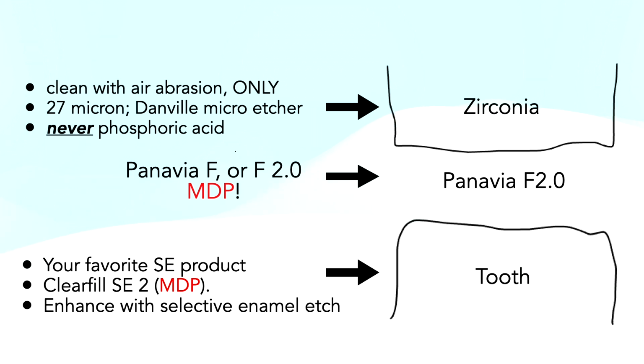That's the first one that came out. Then they changed the chemistry and called it version 2.0 because now it's light cured. But it's also oxygen inhibited. So all of these bondable materials will form an oxygen inhibited layer. But Panavia F2.0 won't cure at all if it's exposed to oxygen. So you can put a thin film on a paper pad and leave it overnight. It won't set as long as you're not exposed to light.